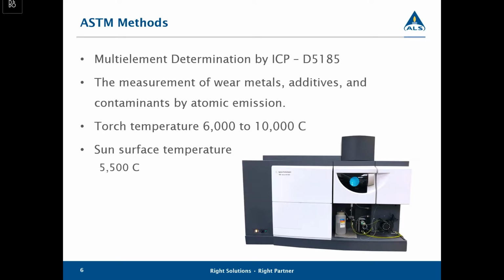That blue glow in the circle that you see is very similar to a welder's helmet, because the torch inside of there is plasma. What we're doing is exciting argon with a very high voltage and radio frequency, and it excites that argon into a plasma that burns very, very hot. Below that, you'll see some tubes, and those tubes help direct the oil up through that plasma, and then it comes out as vapor out of the top exhaust port.